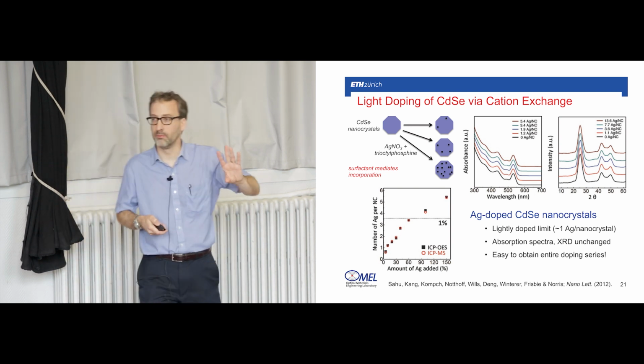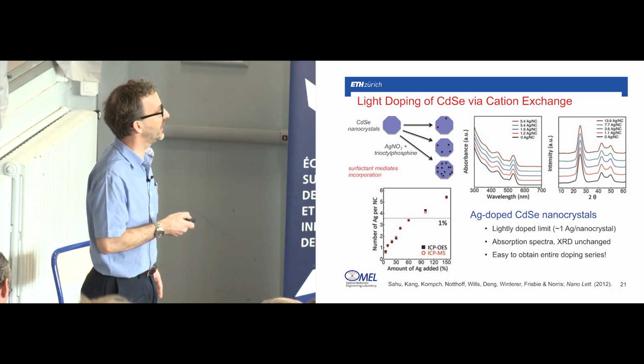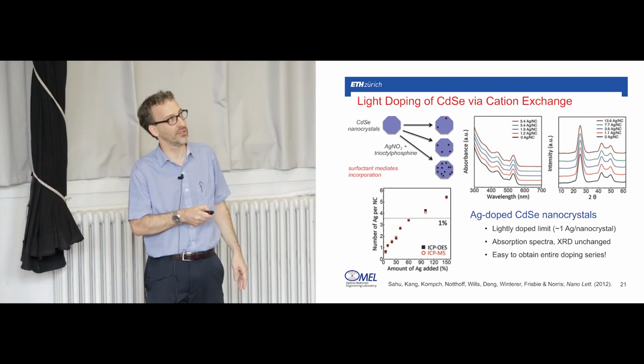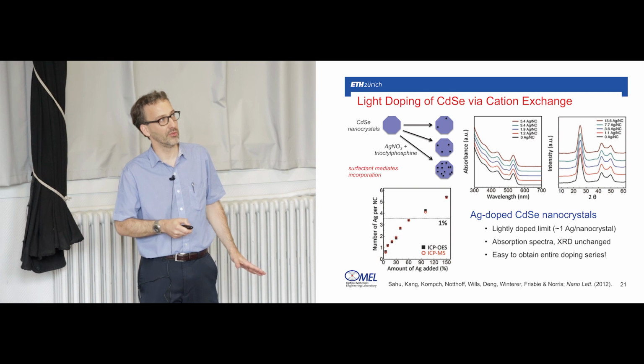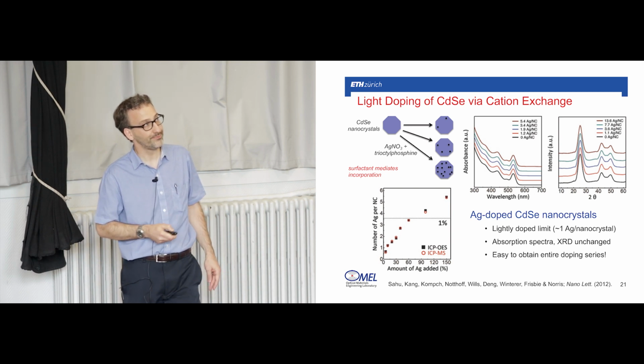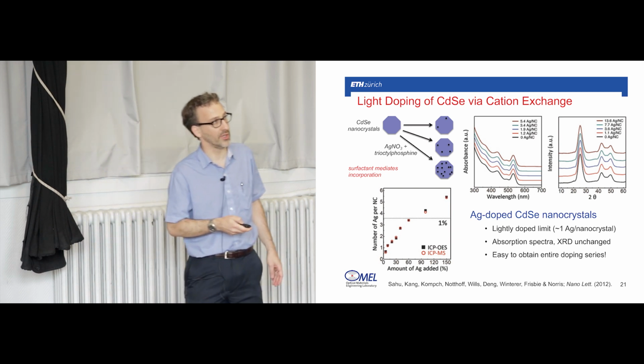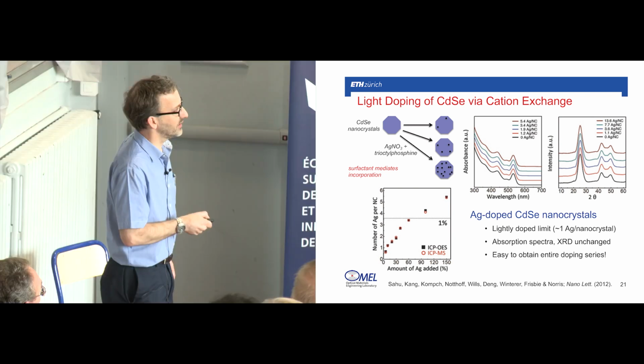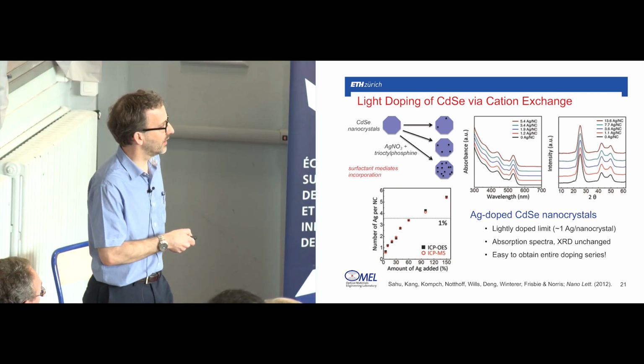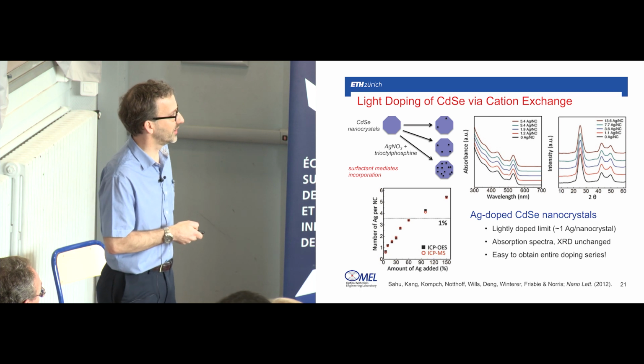Now, to make sure there wasn't anything going on in terms of phase segregation, he looked at the absorption spectra as a function of the number of dopants, and nothing really changed. We'll talk about that in a minute. And in the X-ray diffraction, nothing really dramatic changed as you went up in the number of silver impurities. So he was able to get to this lightly doped limit. Nothing dramatic was happening in absorption or X-ray diffraction.